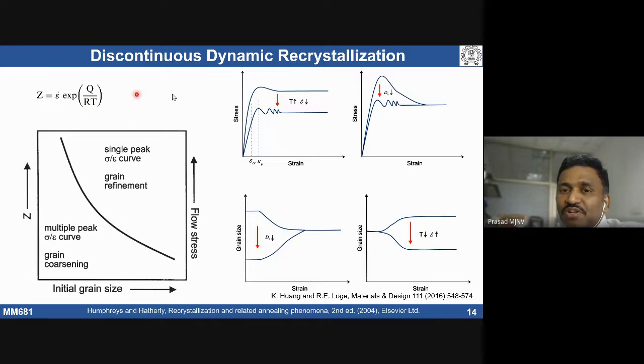So when you see multiple peaks, it means multiple recrystallizations are actually happening. That means complete recrystallization happens, followed by work hardening again, then recrystallization again. After a certain amount of time we see a balance, so finally we get a steady stress. Depending on your initial grain size, temperature and strain rate of deformation, we see changes in the stress-strain curve if the material is exhibiting dynamic recrystallization. Is it clear?